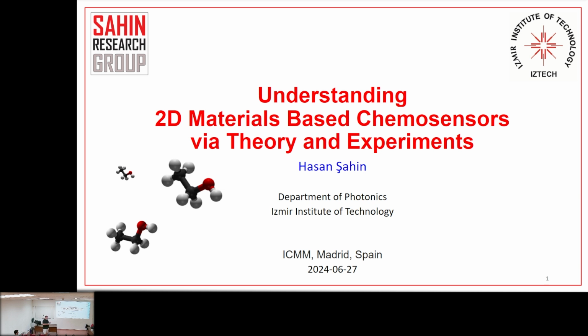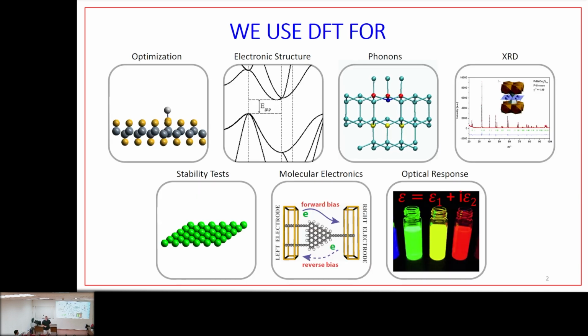I just recently learned about those sensors. And as you know, I'm a theoretician. We calculate structural optimization. As you see here, this is fluorographene, and the approaching atom is a kind of transition metal atom. At the end of this calculation, I can say that this surface is not that stable according to the DFT calculation. As you see here, it's trying to be substituted with 2 fluorine atoms from the surface. So this surface is not that stable against transition metals. By performing DFT calculations, one can reach such conclusions.